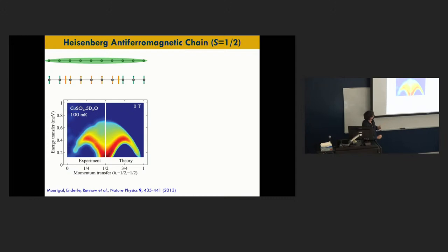And what I see is this: the color here encodes the scattering. So if it's red, it's very intense. If it's blue, there is no scattering, and so on and so forth. And what you see is something that looks like a sine wave here, but there is a continuum of excitations that lives above this. And this continuum of excitations is the signature of fractional excitations. So this experiment proved that this material at low temperature has fractional excitations, and as a proxy, an entangled ground state.